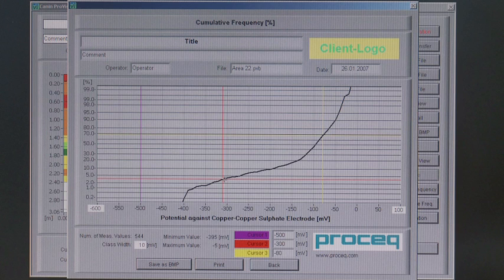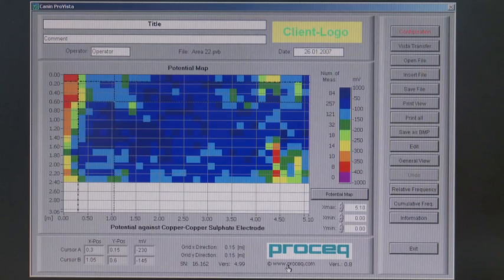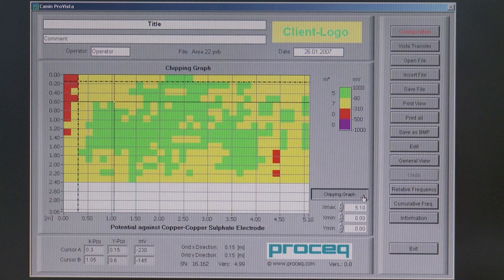It is possible to overlay 2 or even all 3 cursors and thereby decrease the number of divisions. The cumulative frequency needs to be activated at least once for a newly opened file in order to be able to view the chipping graph. Once the cursors have been set on the cumulative frequency graph, the potential map button becomes active. By clicking on it, the visualization switches to the chipping graph. The 4 color regions of the chipping graph are based upon the 3 cursor positions in the cumulative frequency graph. These positions represent potential limits identified by the engineer as areas of equal condition where the concrete has to be chipped to a certain depth for repair purposes.